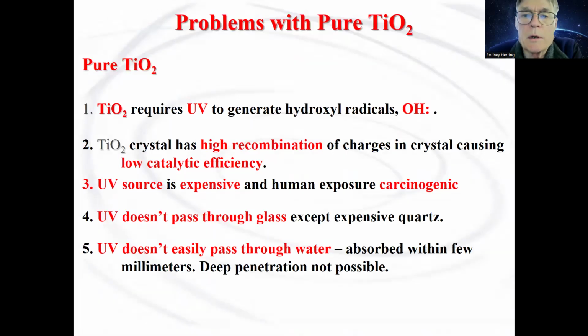The problem with pure titanium dioxide is that it requires ultraviolet light to generate hydroxyl radicals. It has a very high recombination of the charges should the crystals be activated, which creates a low catalytic efficiency. Ultraviolet light is expensive and carcinogenic. It doesn't pass through glass except expensive quartz, and it doesn't easily pass through water. It's absorbed within a few millimeters, so deep penetration isn't possible.